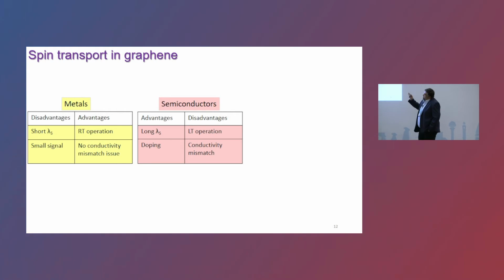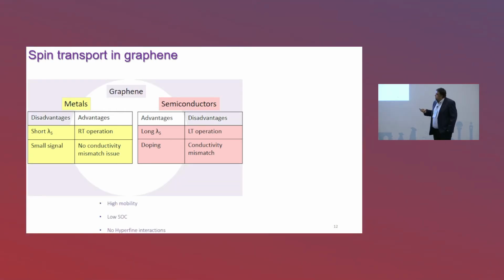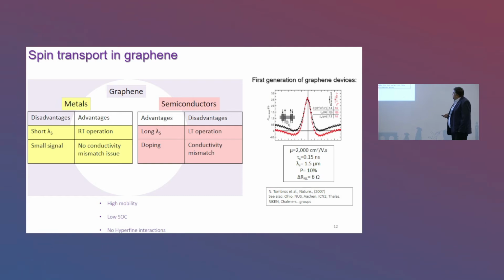So the whole hype with the two-dimensional materials was the following. We were predicting that because the material has high mobility and is made of carbon atoms, which are quite light atoms, you would expect very low spin-orbit coupling strength and no hyperfine interaction. So we were expecting to inherit the advantages of both metals and semiconductors. And the first devices were successful. A group in the Netherlands, Bart van Wees' group, demonstrated that spin transport works up to room temperature with relaxation lengths above a micron.